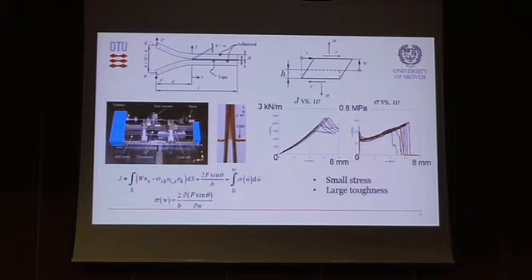This is the typical specimen configuration that we have been working with a lot, the DCB specimen. If you take the integration path in different ways around the crack tip, you get from the loads, this expression, the force, the rotation at the loading points, divided by the width of the adhesive layer. If you take an alternative integration path around the crack tip, and assume that J is path independent, then you get this expression, and they should be equal, and then you can differentiate, and you get the Irwin-Kies law for monotonically increasing separation.